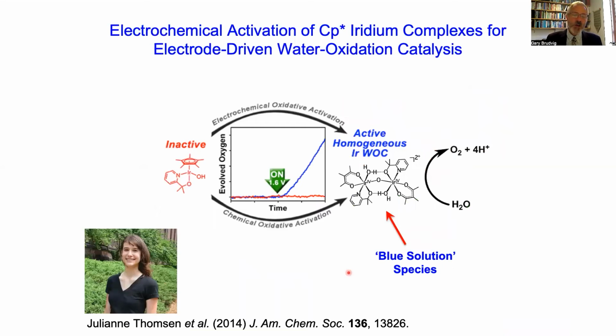So I'll just describe our best catalyst to date, this iridium dimer. We can form it from an iridium precatalyst. It's an iridium pyridine-alkoxide complex with a Cp* ligand. And we can either chemically or electrochemically oxidatively activate it to form this dinuclear iridium complex, which we call our blue solution species. And we can illustrate its catalytic activity by showing the evolved oxygen as a function of time after we apply a voltage.